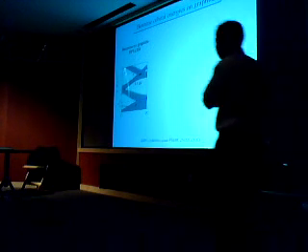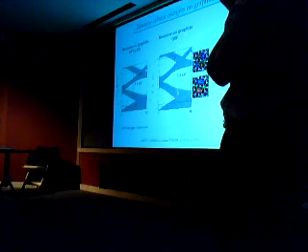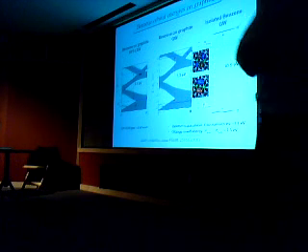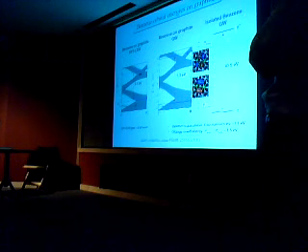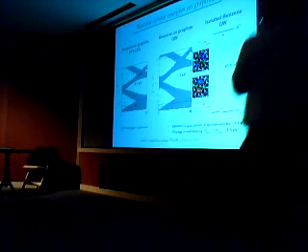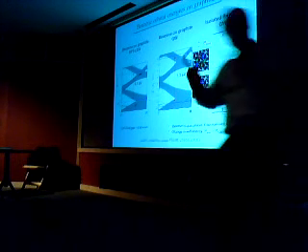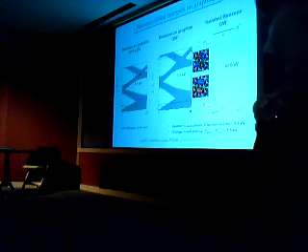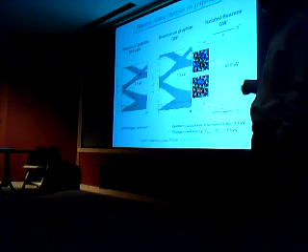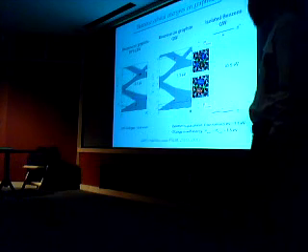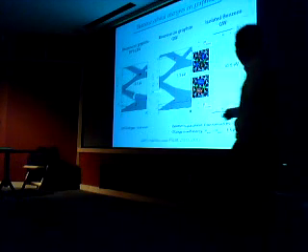Now, suppose you put benzene on graphite. Within LDA, actually not much change. You still have a gap around 5.1 electron volt. In the GW calculation, you have a HOMO-LUMO gap of 7.3 electron volt compared to the isolated molecule of 10.5. So you see that as you bring the benzene molecule toward the graphene surface, you actually reduce the gap by 3 volts. But LDA doesn't really give you the right answer because it's off by 2 volts.